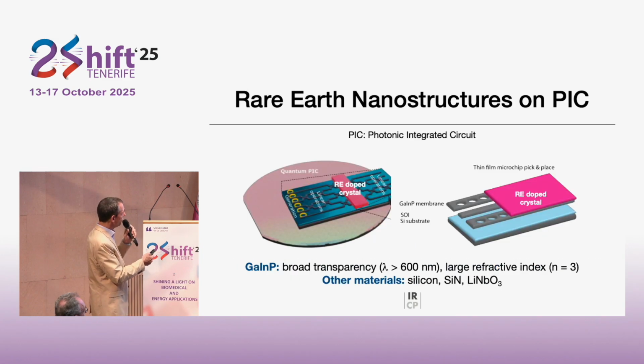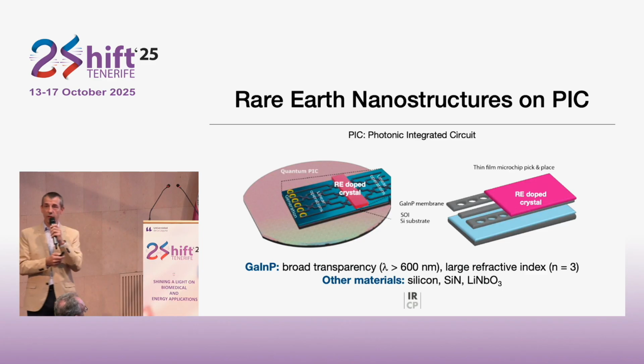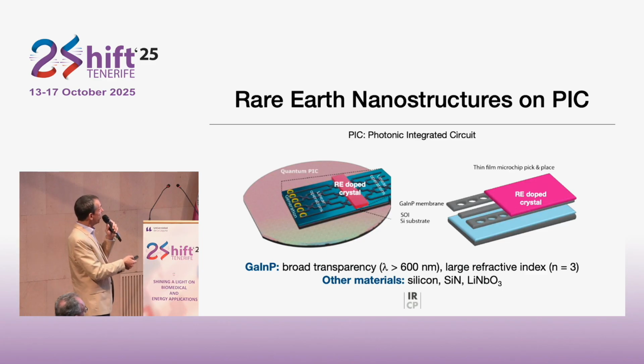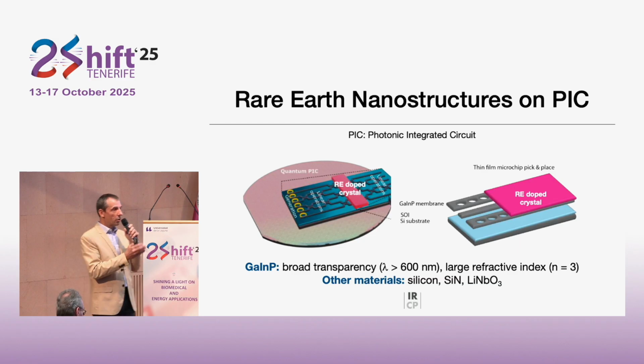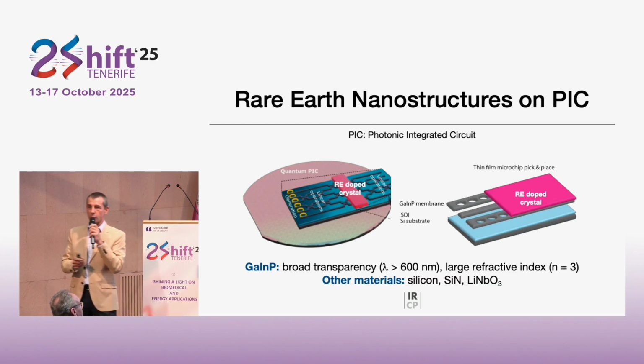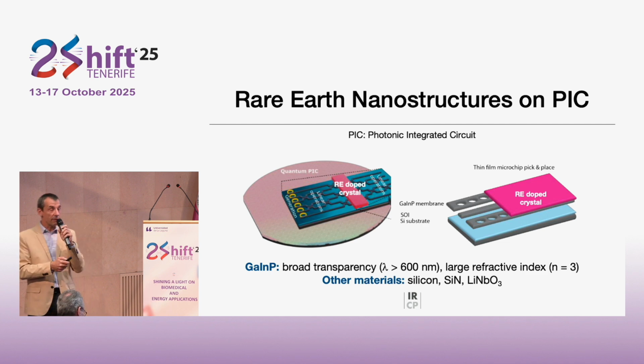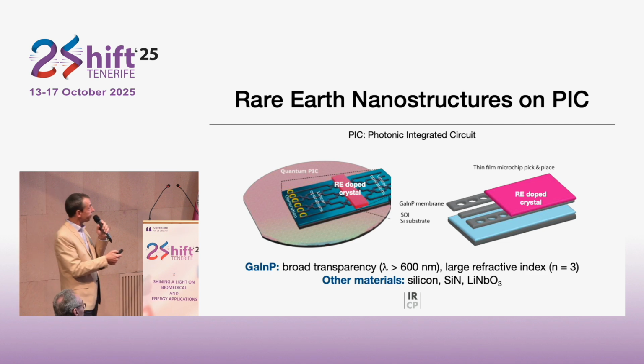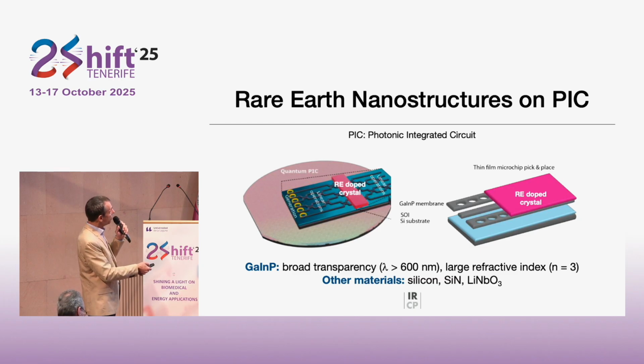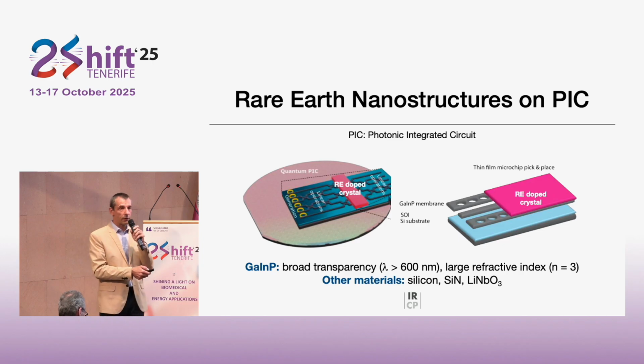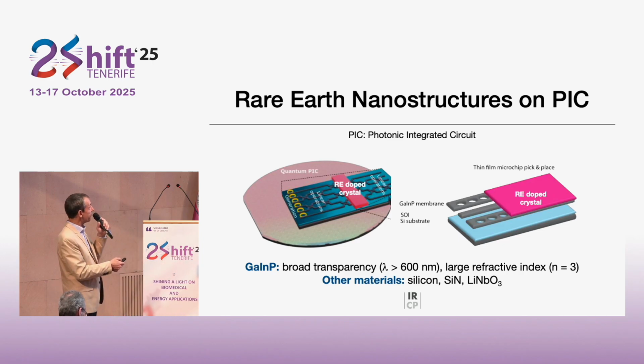So one idea to couple rare earths to these integrated circuits is shown here. Imagine you have this chip with these waveguides or different structures. And then what we could do is simply try to position a rare-earth crystal on top of this circuit, and in this way couple the rare earths to these structures. So here you see a zoom on this. For example, here we would have some optical resonators that could couple to the rare earths.